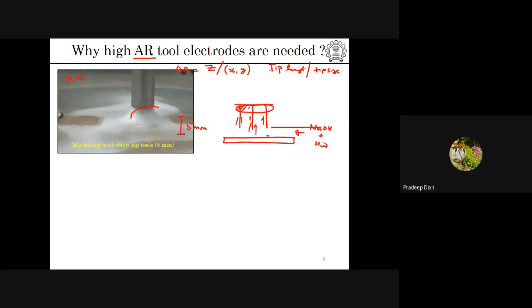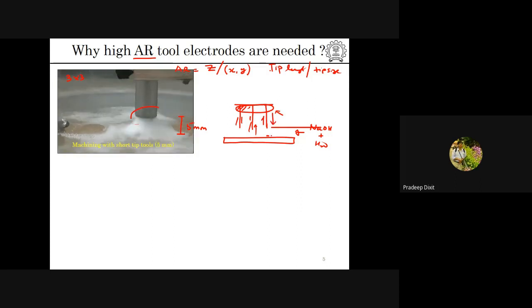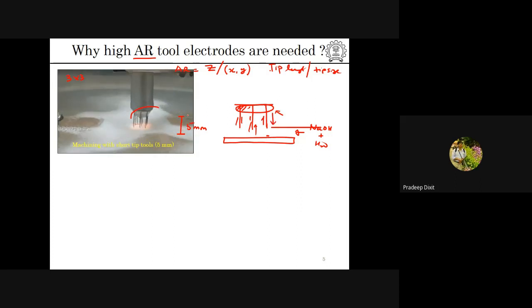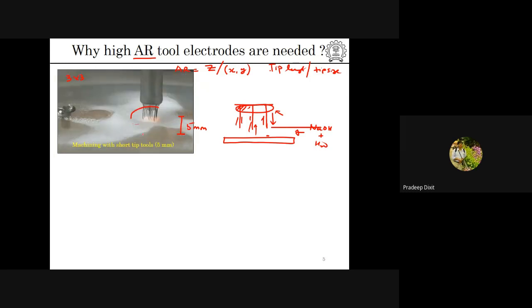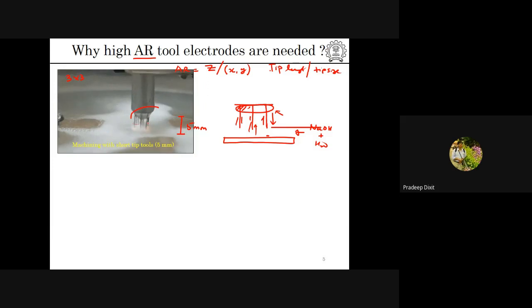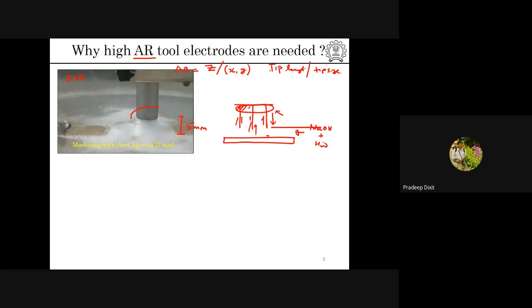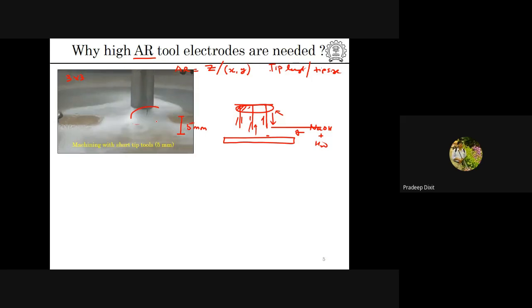Naturally, after some point of time, this water vapor cools down and forms a bubble, and this bubble after some time drops down because of gravity. Once it has dropped, this is a kind of short circuit phenomenon. The machining process automatically stops here. So it means that the electrochemical discharge machining process is not continuous in nature. It's basically interruptive, which is very bad from the overall performance point of view.